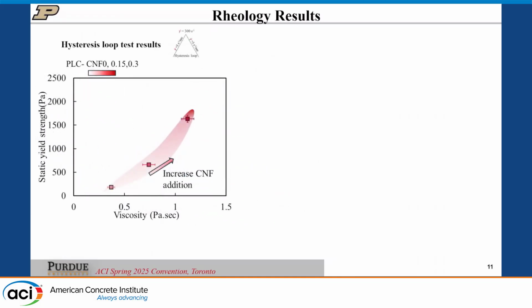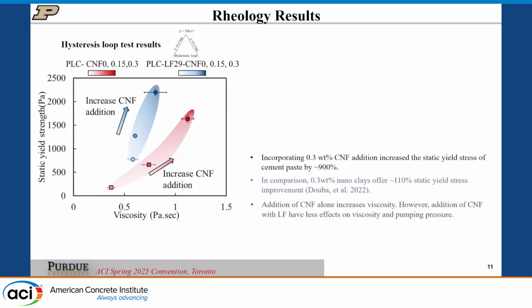The other thing is the interplay between viscosity and static yield stress. Having such an increase in static yield stress isn't very useful for 3D printing if viscosity increases at the same rate. Looking at the system with viscosity, in red is the system with CNF without additional limestone - we're gaining static yield stress, but also significantly gaining viscosity. That means even though the system can stiffen, it's still going to be very viscous, so we'll have challenges pumping and extruding.